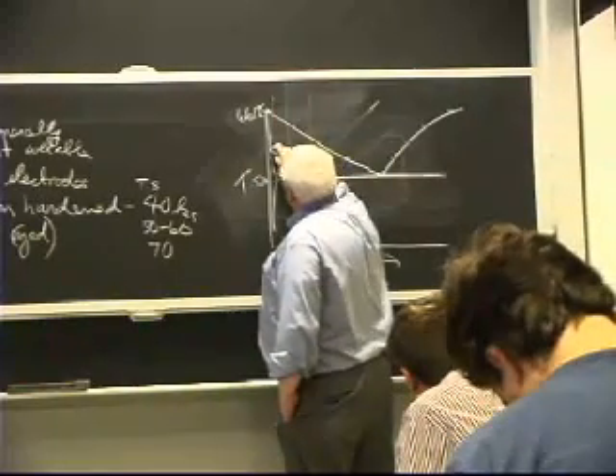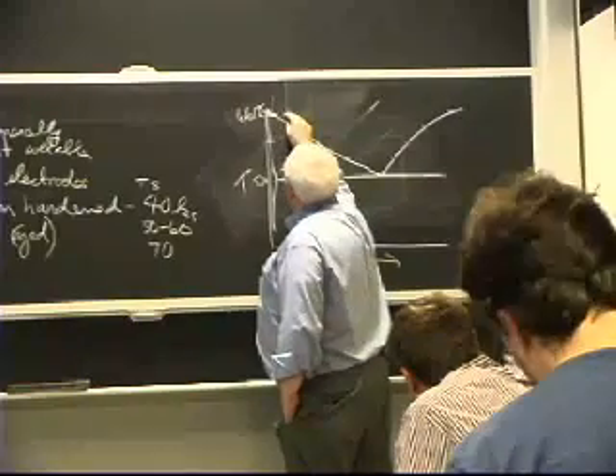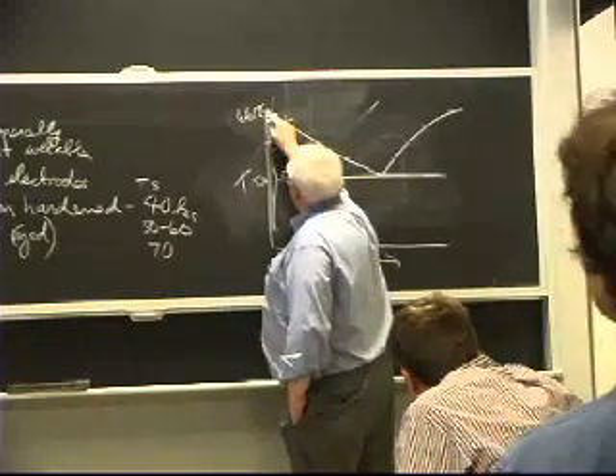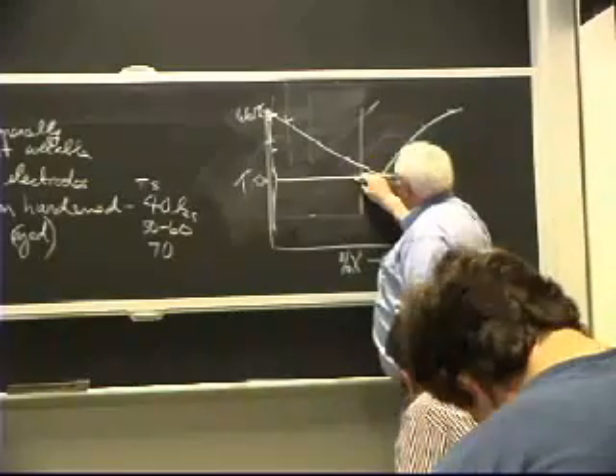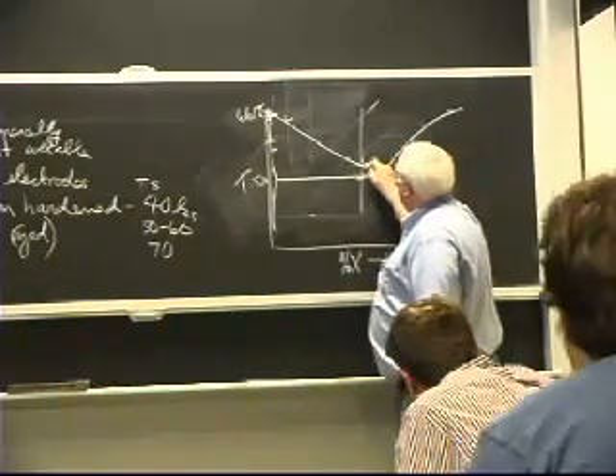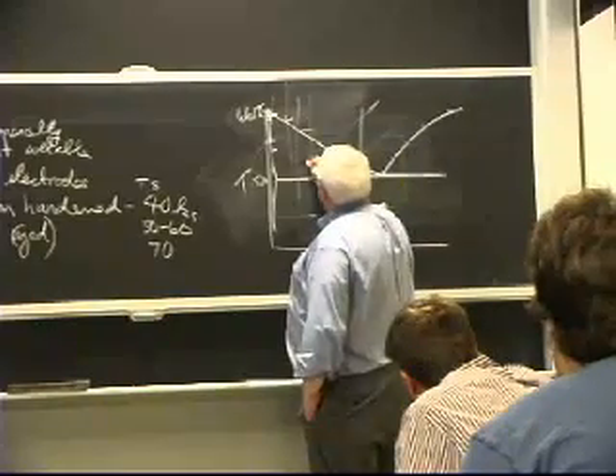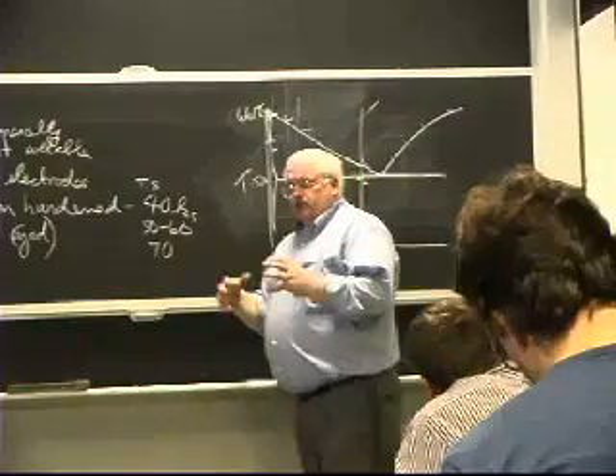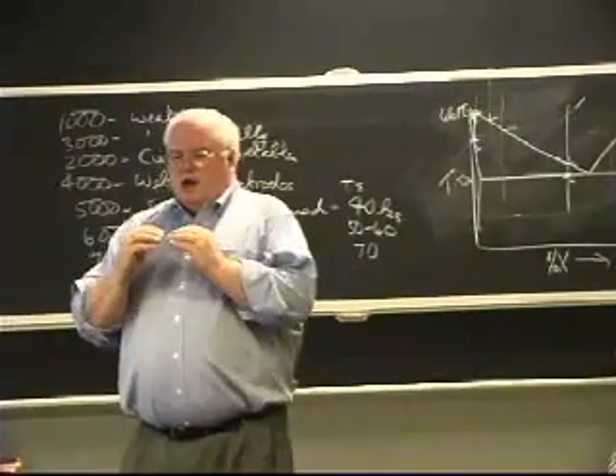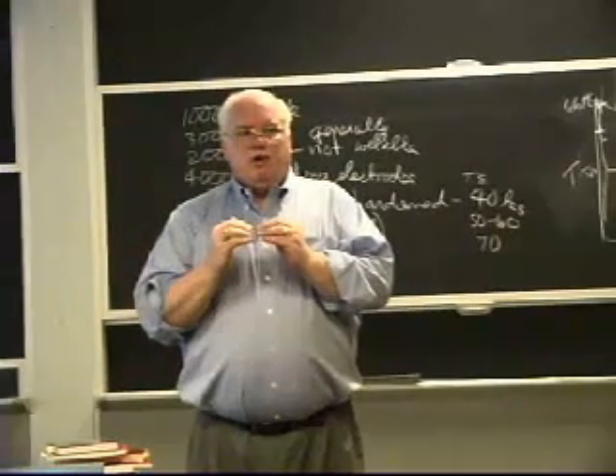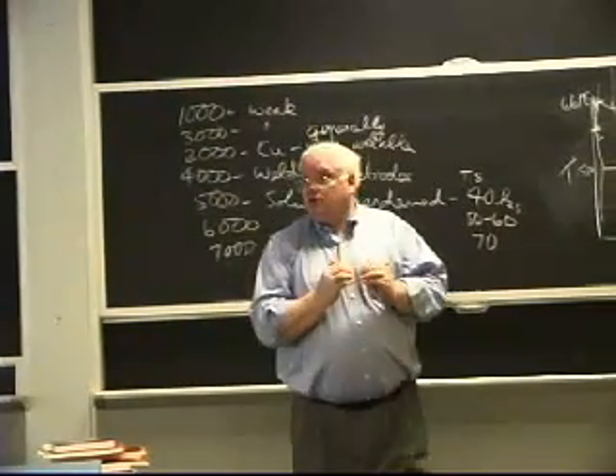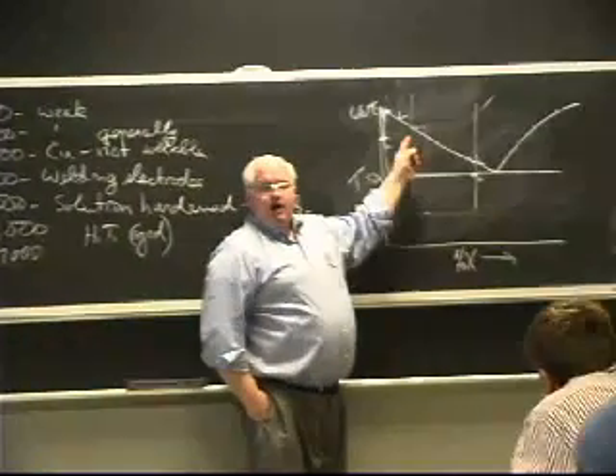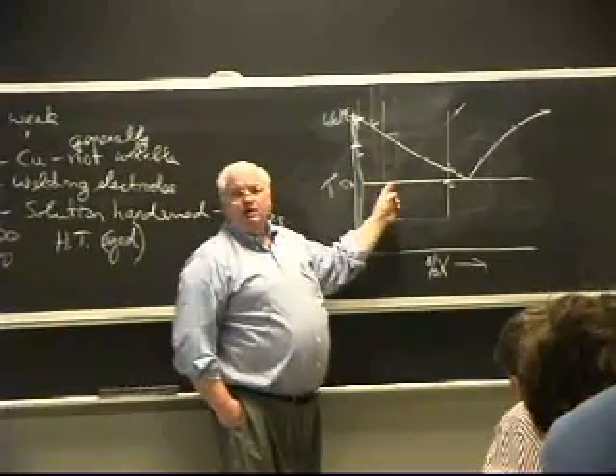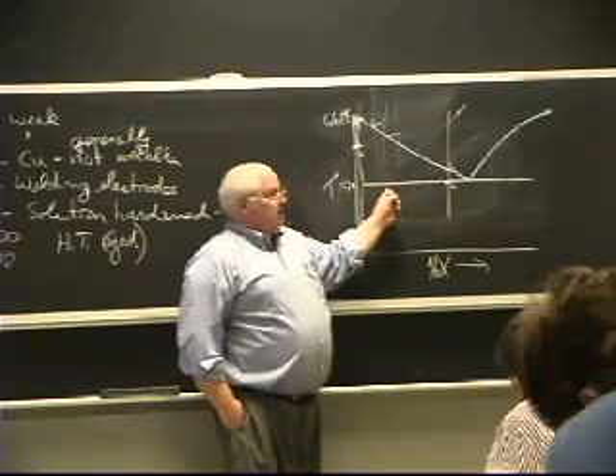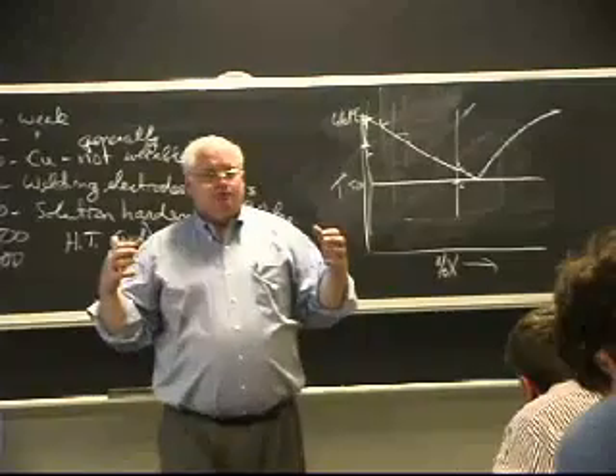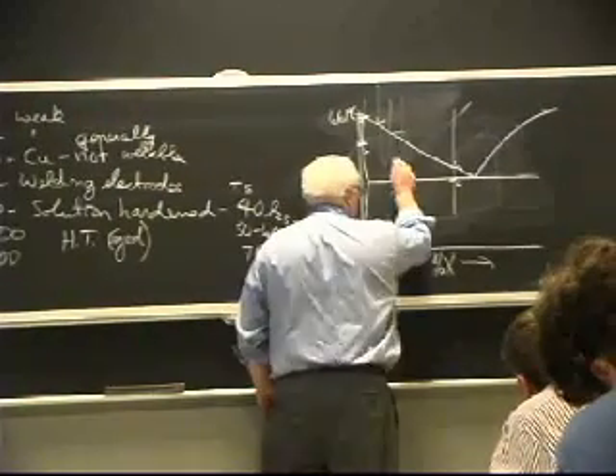If I'm a very lean alloy with only a couple of percent, my solidification range from liquid to solid is this temperature difference. If I'm near the eutectic, it's also similarly small, between liquid and solid. In this intermediate region, I've got a much bigger solidification range. And aluminum actually shrinks about 6% on solidification. So if I have this rigid aluminum structure and the weld metal wants to shrink, when it's like a Slurpee, in the liquid-solid region, with a big liquid-solid region I have a bigger delta T, and a bigger delta T means more solidification shrinkage. So I'll just rip that Slurpee apart due to the shrinkage stresses. It's all proportional to the delta T.